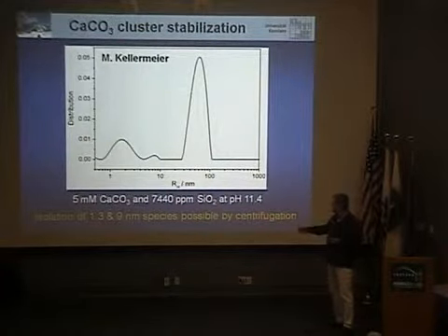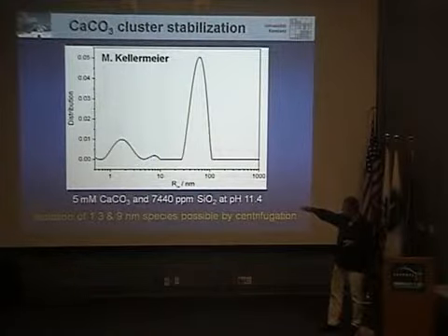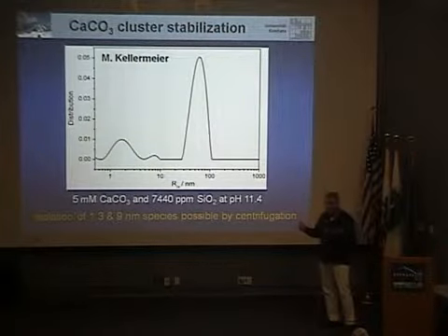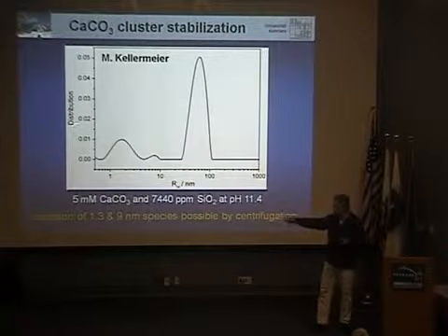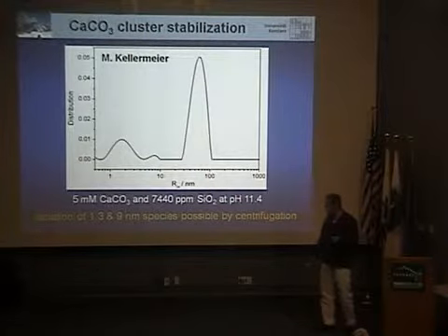And you see a dynamic light scattering experiment here. So you have the prenucleation clusters. Then you have a first sort of aggregates, which is 9 nanometers big. And then you get about 60 nanometer large aggregates. And if you take that solution and centrifuge it, you can take away the large aggregates, and then you are only left with the prenucleation clusters and their first aggregates, which are about 9 nanometers big.